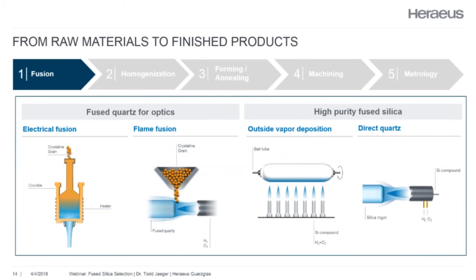So fusion is how the material is made. The production method that's used really determines the properties of the end product. We will refer to the end product as either a natural fused quartz, which is on the left side here, or a high purity fused silica, which is on the right side here. The fused quartz begins as a crystalline grain as the precursor. Although we can produce this either in electrical furnace and crucible, as you see on the far left, or we can do this with a direct flame fusion, the physics are very similar.